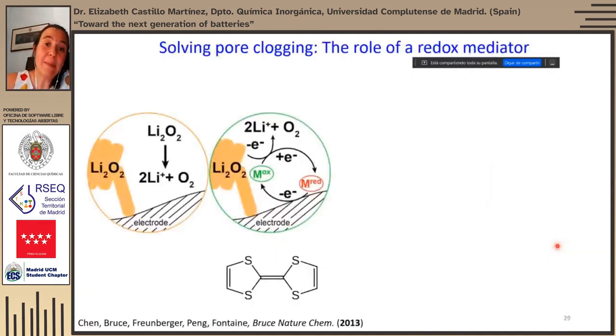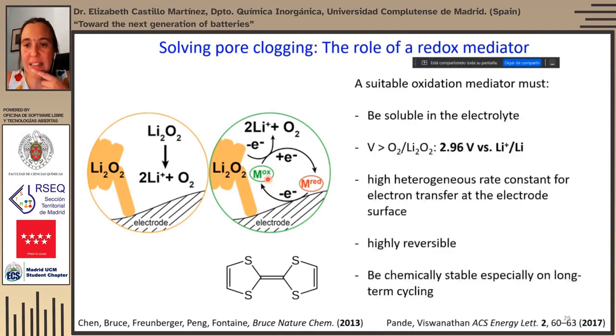And you start by oxidizing the lithium peroxide in contact with the carbon. So once this is all oxidized, the remaining lithium peroxide gets disconnected from the carbon, and therefore you have lots of dead weight, which is not reversible. So in this sense, the main strategy has been to use redox mediators, which are soluble in the electrolyte, and actually, instead of reacting with the lithium peroxide particles in the region where they are in contact with the electrode, they do react with the bulk of the lithium peroxide in solution. And this proves to be a very big improvement in reversibly reacting this battery chemistry.